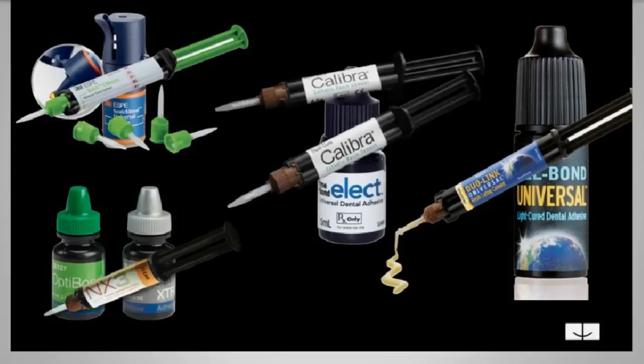So if you can't get full light cure in it, if you have a zirconia restoration and you can't get light through it for the total polymerization, then there is a dark cure that happens by itself. But if you use NX3 with Prime and Bond Elect, you won't get that. Vice versa, if you use a Prime and Bond Elect and you put a dark cure, self-cure activator in it, it might not work as well with NX3. So when you are using these systems, use it as a system.